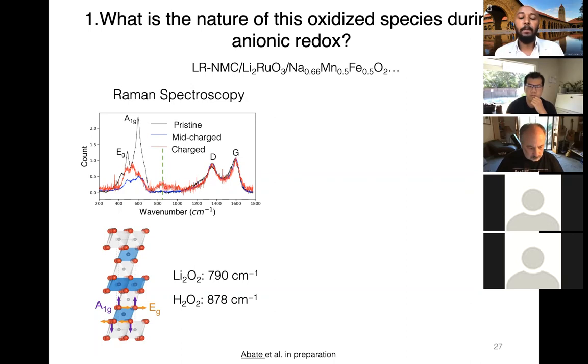As you can see, the Eg and the A1g bands are coming from a vibration in the different planes of the material. The D and the G are coming from the small amount of carbon we add to improve conductivity. But the most important change I would like to draw your attention to is what happens when you charge. So when you charge, as shown in this red curve, we have this new peak forming around 800 wave number. And this 800 wave number has been correlated with a peroxide presence in a given material.